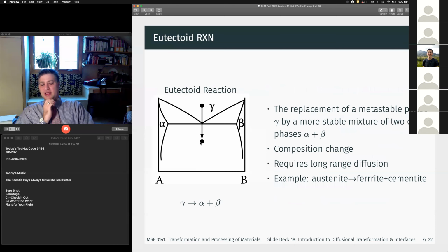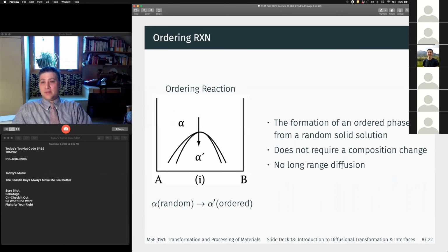We also have eutectoid type reactions, right? Where we'll go from single phase gamma to two different phases, two brand new phases, in this case, alpha and beta, right? So this also requires long range diffusion, right? An example of this known in steel, right, is our austenite to ferrite plus cementite reaction, right? That we get in carbon steel, right? We also have a whole host of reactions that don't require long-range diffusion. So ordering, right? When we talked about solid solutions, we talked about how we can go from a random atomic distribution, right? Where there are no preferential sites, to an ordered structure where there are, right? Again, this doesn't require a composition change and it doesn't require long-range diffusion.